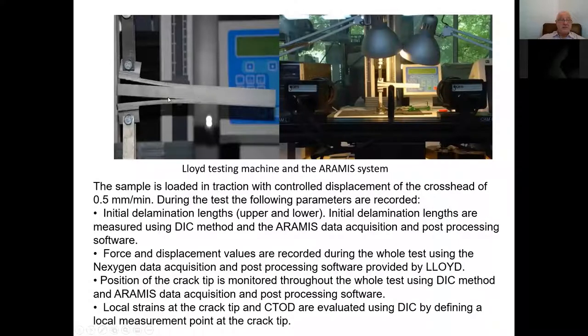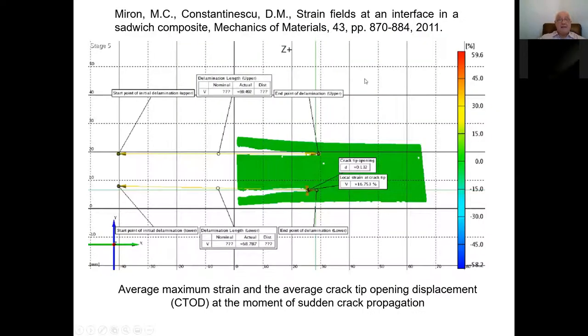The core was a foam. And as I mentioned before, even if you consider two initial artificial cracks of the same length, one of them will go further and will grow, the other one will stay at its initial position. So we were interested in local strains at the crack tip, and we have done all kinds of measurements of the opening and propagation of the crack at the interface.